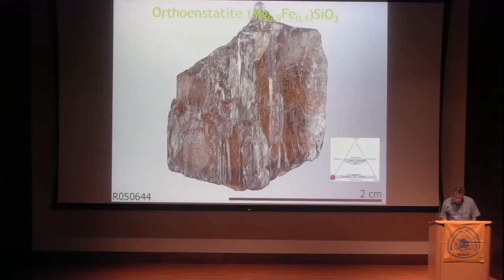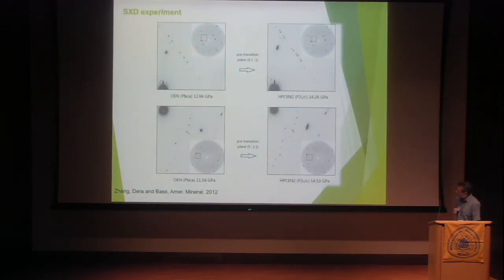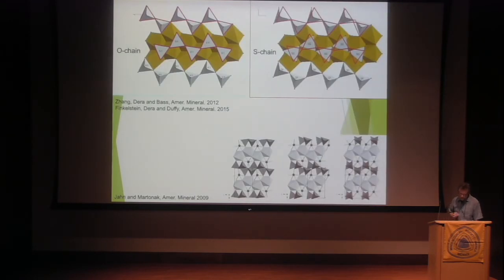But when we started squeezing these samples to higher pressures, for example, taking the enstatite end member, which has magnesium as the dominant cation, this is work that was done in collaboration with Jin Zhang and Jay Bass, a pretty long time ago. We found that these samples at pressures higher than what was previously explored undergo additional phase changes, which change symmetry and affect density a little bit. So we found that orthopyroxene at about 12 gigapascals, depending on the composition, 12 to 14, undergoes a structural phase change which changes the symmetry from orthorhombic to monoclinic, but preserves the topological arrangement of layers. The main mechanism for this phase change is a rotation of tetrahedra and a change in the geometry of the corrugated silicate chains.